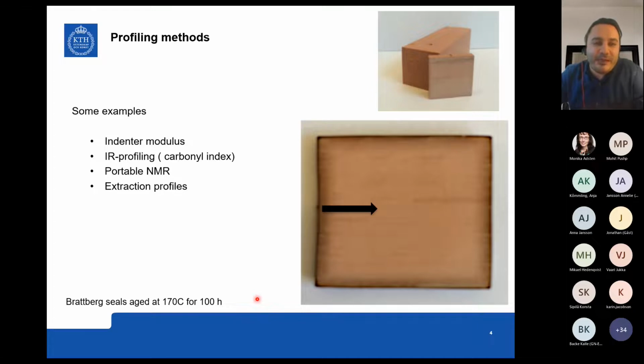So we did a lot of profiling during my PhD work, and some examples of profiling work are indentation modulus, which Anya also showed, where you're looking at the surface hardness of your sample, or infrared spectroscopy, where you're looking at the carbonyls. The carbonyls are an oxidation residue that you get from polymer oxidation. And we also have a portable NMR, which I will talk about briefly, and give you a bit of background and some know-how about.